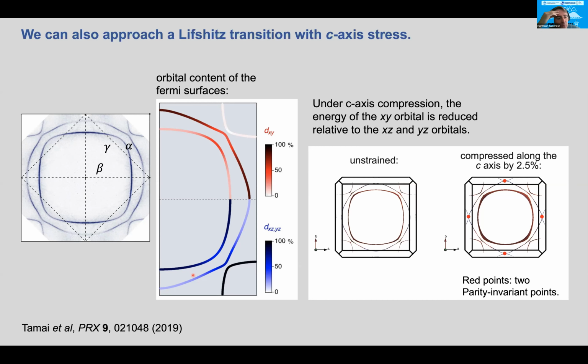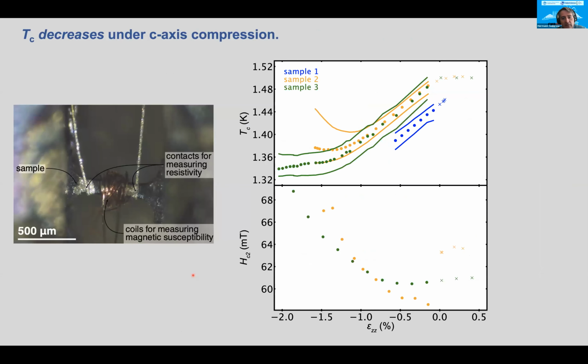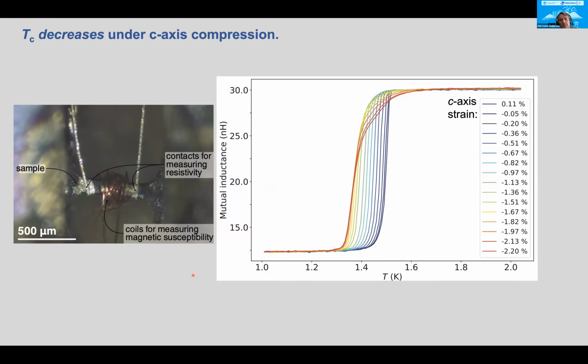I just want to make the point that pure strontium ruthenate has an extremely small upper critical field. It's nearly a type 1 superconductor, and this is quite a strange situation. So actually, I am not surprised that whatever you do, you increase the critical field. Now, could you present your last measurements where you show the resistivity? These ones, yes, the previous transparency. I wonder why it seems that the transition width increases when you increase your strain. Is this right? There are very few defects in this sample. These are usually very pure systems. But what happens with the defects when you apply strain? Do they move? And if they move, what would happen to the sample?